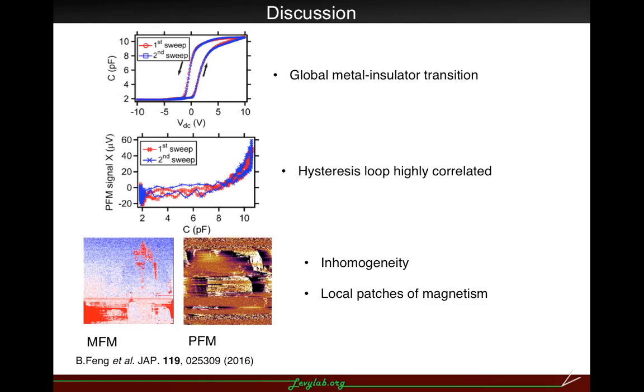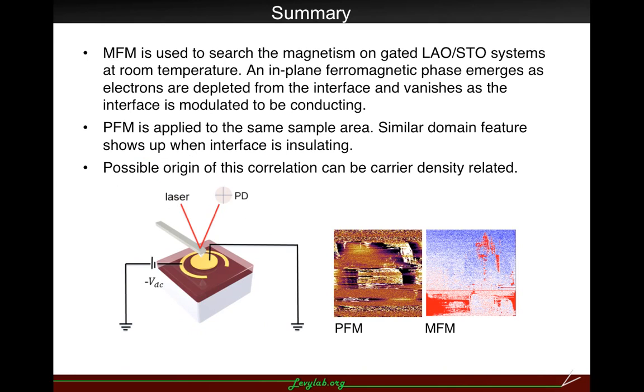The small patches of magnetic domains we observed are due to the inhomogeneous distribution of the carrier density, and this inhomogeneous carrier distribution will lead to different piezo responses. So both MFM and PFM are carrier density related. In this way, they are highly correlated.